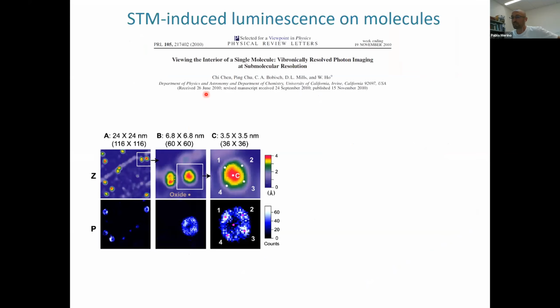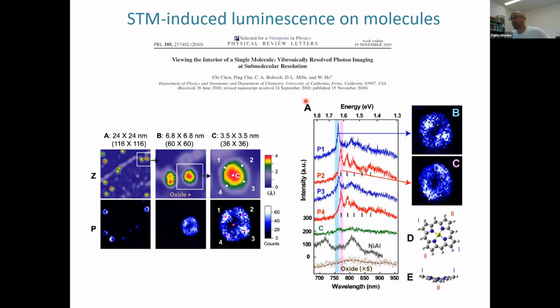So the fact that there is light coming out from a tunnel junction in an STM is known almost from the beginning of the STM field itself. But the field really had a boost since 2010, when the group of Wilson Ho published this paper, where they were able to see submolecularly resolved photon maps of a single molecule. In this work, they were studying manganese porphyrin on top of a thin aluminum oxide layer, and they were able, by injecting current into the molecule, to generate electron hole pairs that recombine as photons.